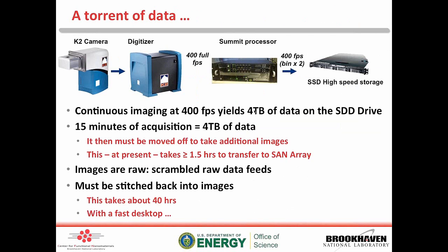So some things to think about. If you have 400 frames a second at 2K by 2K, that's 4 terabytes, and it turns out that we can acquire a total of 15 minutes at 4 terabytes. So that's a good amount. We can actually basically use the microscope in the morning, be selective in our data acquisition, and collect 15 minutes of data, and then move it off, say at lunch, a nice long lunch, and then come back and do more work in the afternoon. It takes about an hour and a half to transfer it over to the SAN array.